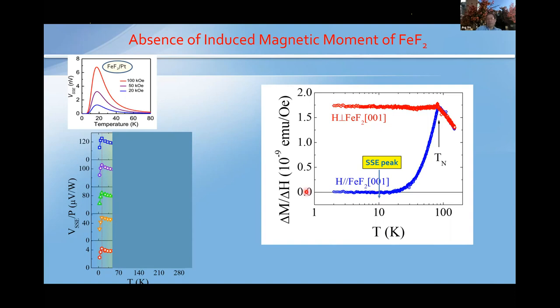So this allows me to conclude that this low temperature peak, the spin Seebeck peak, does not originate from the induced moment, right? We can say that. So we're dealing with the z-axis field. This was expected before, based on the high field, the spin flop field.